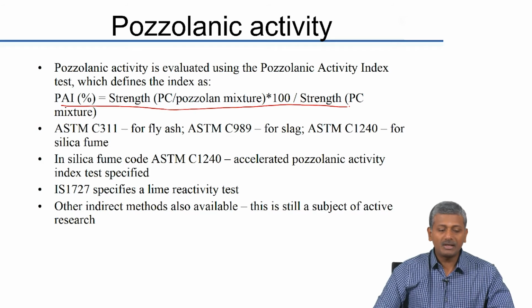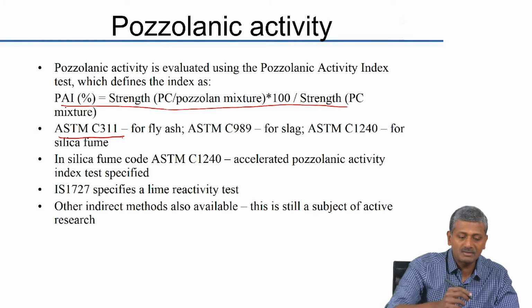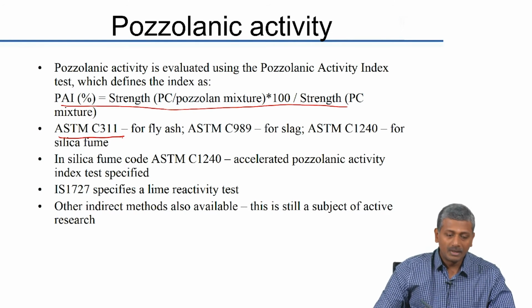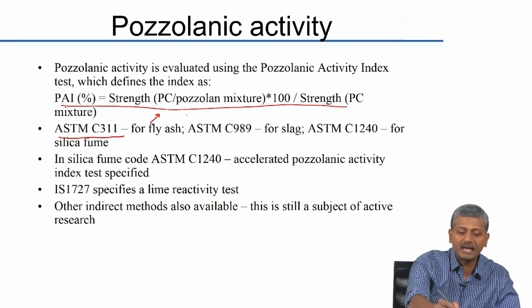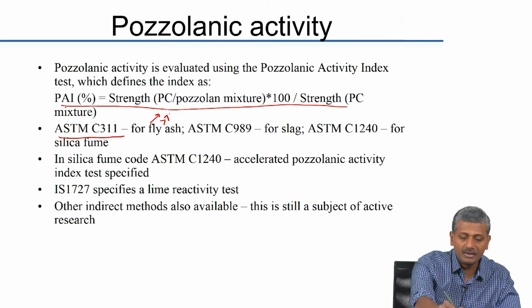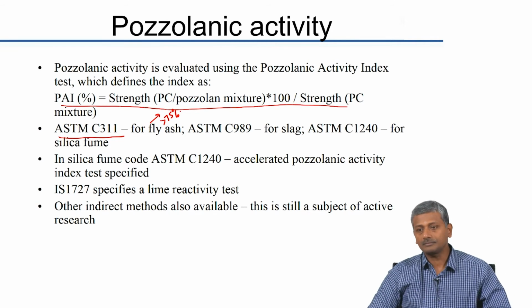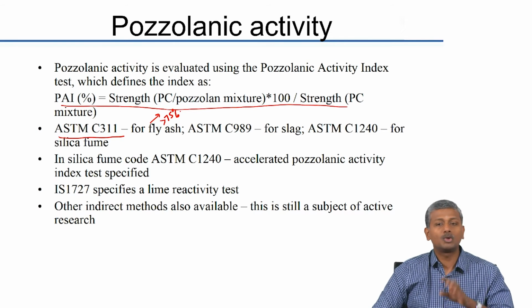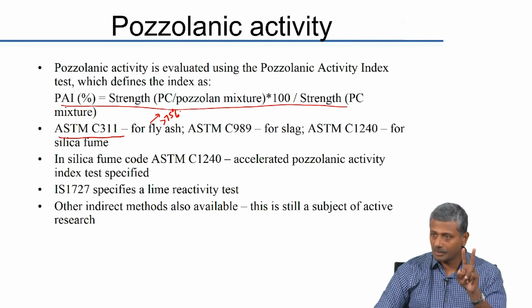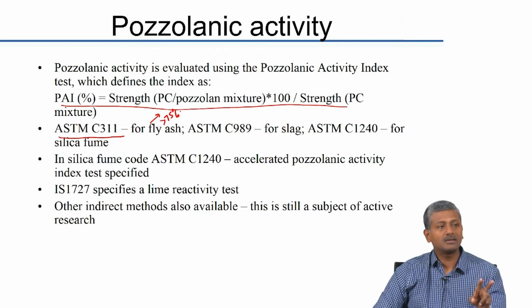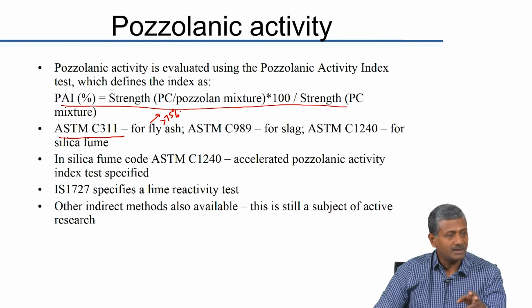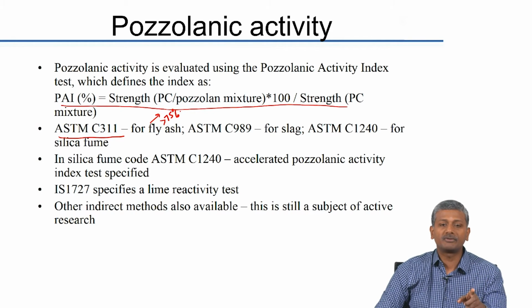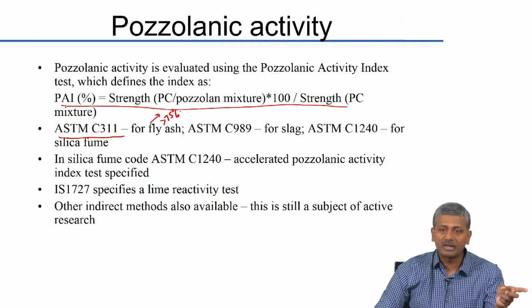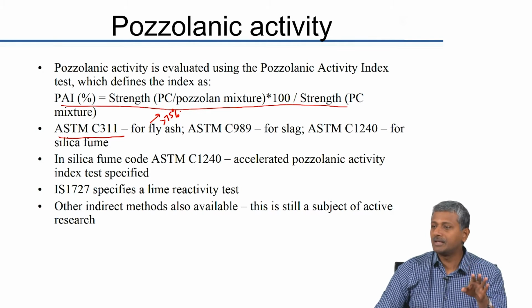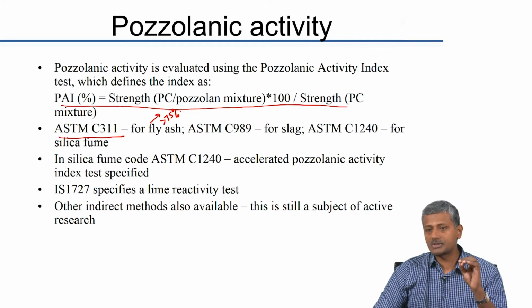Generally, for fly ash, ASTM C311 is the standard that is typically used, and as per that, your pozzolanic activity index with fly ash should be greater than 75%. That means when you replace cement by 20% fly ash, the strength of the fly ash cement mix at 28 days should be at least 75% of the strength of the plain Portland cement mix. If it is greater than 75%, then that fly ash is suitable for use as a pozzolanic material.